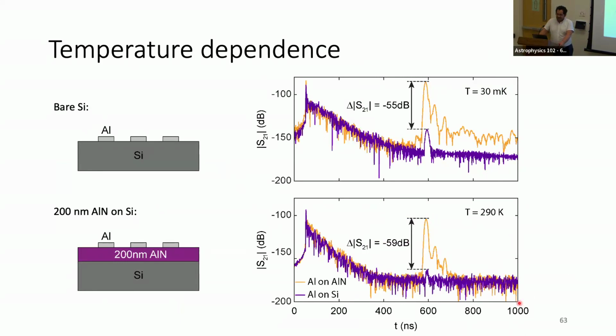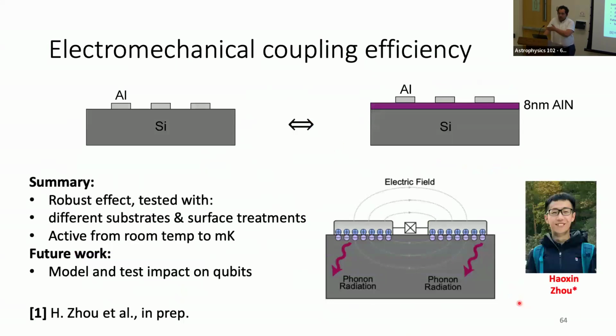So is this something I should worry about? Is it something I should use? As a way to calibrate, we compared the transduction efficiency with some aluminum nitride thin film. We compared the S21s. This is not a perfect calibration, but it gives us some sense of the strength. Using a reference film, we think that the effect corresponds to having about 8 nanometers of aluminum nitride at the interface.